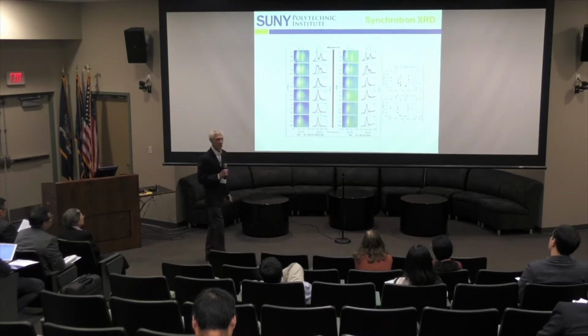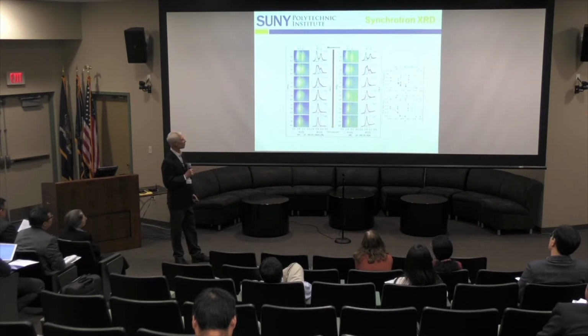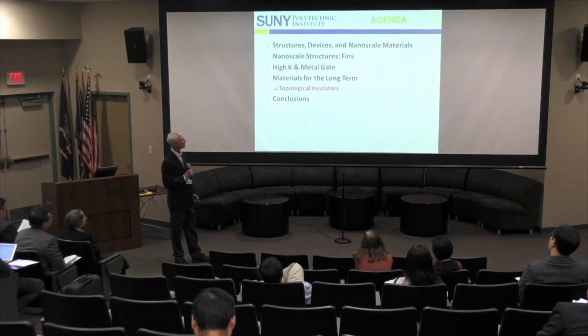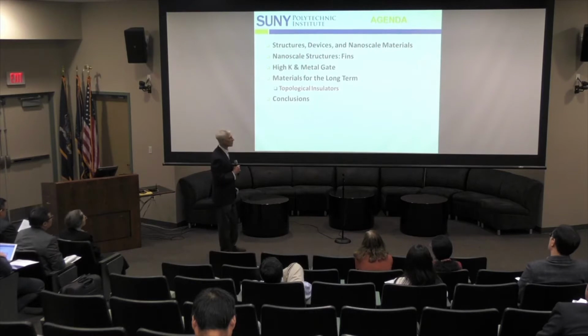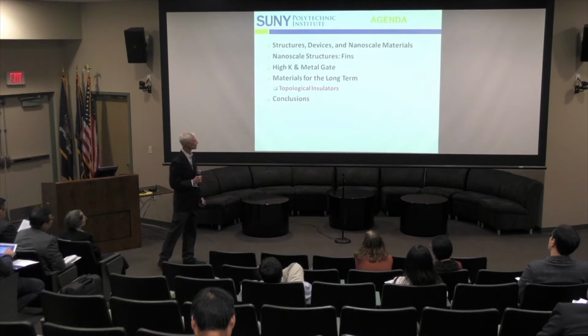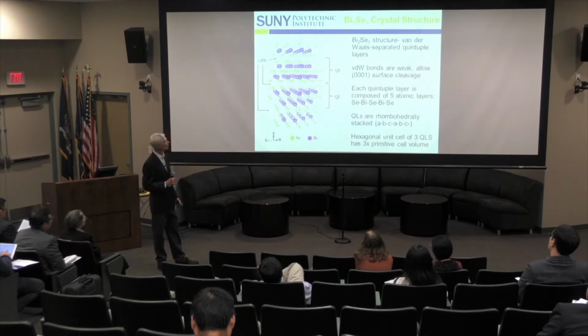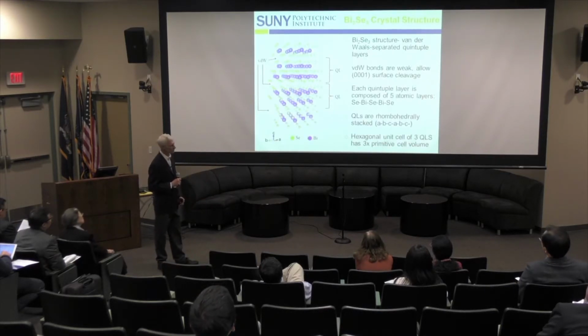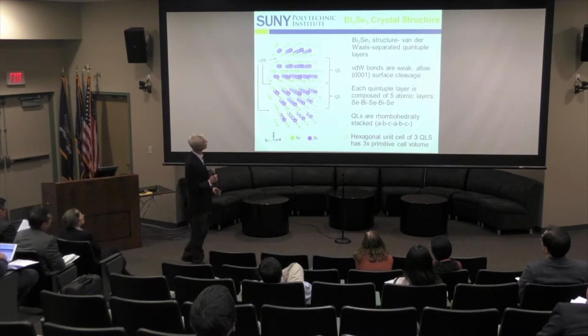So this kind of information can be determined, but it turns out that the ferroelectric phase is really hard to get good diffraction data on. We've been working hard on that. And there's different things in the literature that don't always match up with your own observations when you're doing these sorts of measurements. So let's quickly turn to topological insulators, in particular bismuth selenide, which is a research material,